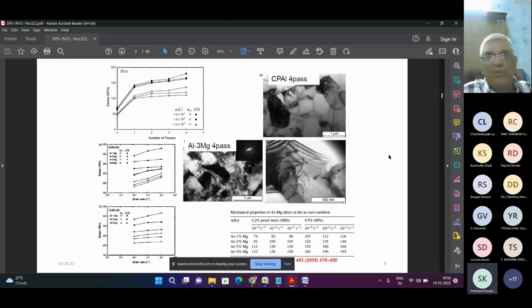What we have done is we have evaluated the yield strength, sigma YS, and UTS also, on the left side top three graphs. Why? Because we have pulled at different strain rates. We wanted to understand the strain rate sensitivity of each material and see how the strength changes if you are increasing the number of passes. From zero pass, if the material is having 80 MPa strength, then suddenly it has increased to 100 MPa yield strength, and it has gone to more than 120, 130 MPa when it went to 4 pass samples. So this is the way yield strength can be calculated.